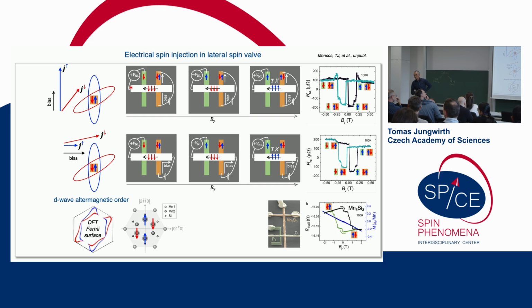I have a very different question. I'm intrigued by this ordering of 4 out of the 6 spins. These are manganese d-orbital, probably large moments sitting there. So is the idea that the moments that you indicate without an arrow are kind of pointing in an arbitrary direction? Yeah, they don't have a net magnetization, and this is seen in neutrons. But you might wonder why these 4 and not, for example, these 4, right? This is actually energetically equivalent, identical, and we indeed could have these variants. In the sample, you can have either these 4, or there are 2 other possibilities where you have 4 occupied. Now, if you go through this argument, then 1 out of the 2 will give you exactly the same polarization of the current, and the third one will give you none, will give you 0.